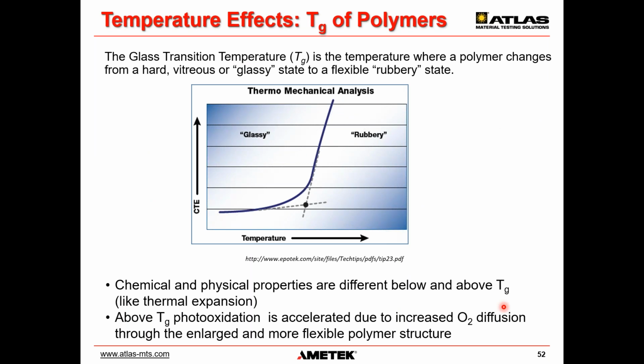Another reason why conducting tests at higher than maximum induced temperature can be a problem is the fact that the material may approach the range of the glass transition temperature. This is the temperature where a polymer changes from a hard glassy state to a more rubbery state. Both states have different physical properties and therefore weathering behaviors, different diffusion coefficients, migration is different, etc. The problem is that for some polymers, especially coatings, the Tg of these systems is often quite near the typical black panel or specimen temperatures. And this can lead to erroneous interpretation of degradation rates, if you are not aware of that.